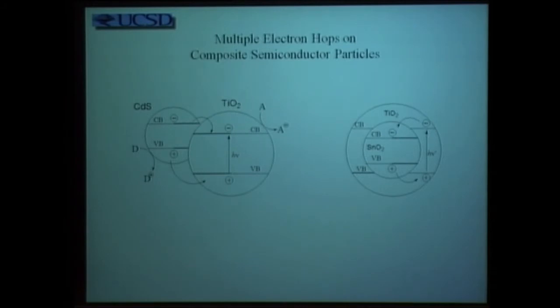For example, you can have cadmium sulfide as a semiconductor bound onto titanium dioxide. And this represents one way by which doping takes place, generating the excited state of TiO2 with charge-separated cations and anions. You can do this, as shown on the left side, by having cadmium sulfide on the outside. If you had a different active catalyst in the middle, as shown on the right, your reactivity would be dominated completely by the surface interaction with titanium dioxide. So we've had a great deal of fun in looking at the inorganic chemistry of bringing together these kinds of molecules, putting small amounts of oxidizers or reducers into the species, and allowing it to undergo defined reactivity that follows from it. Let me give you an example of that.